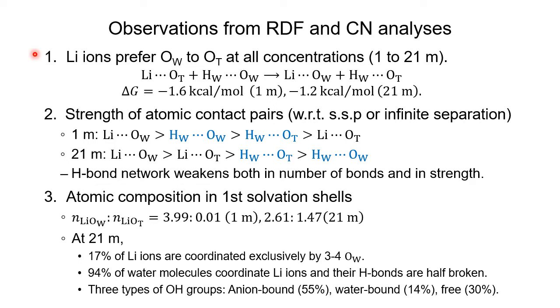From this analysis, we found that lithium ions interact more strongly with water oxygens than with TFSI oxygens at all concentrations, but the gap narrows at higher concentration. Also, we can quantitatively determine the strength of atomic contact pairs, which shows that the lithium water-oxygen interaction is the most stable at all concentrations, and the hydrogen bond network weakens with concentration. Also, lithium ion is coordinated by 4 oxygens either from water or TFSI, and the fraction of OT increases with concentration.